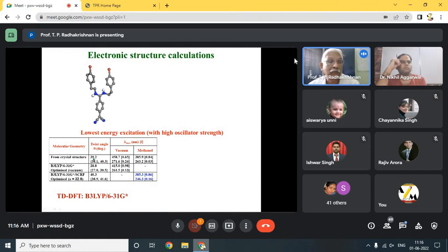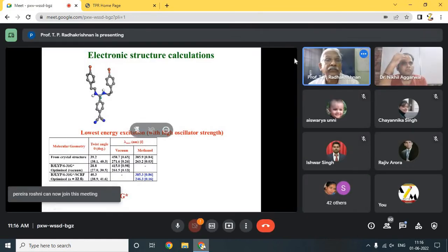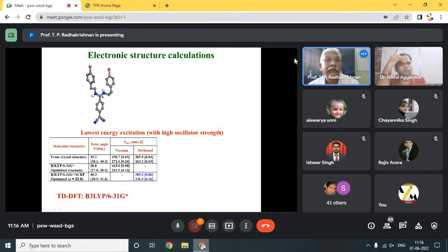as this picture shows. For example, just look at these numbers here. The twist angle, because these molecules are highly twisted. I forgot to mention this. That is this nitrogen atom here, the blue atom, this carbon, the following carbon, and the carbon here, they are not in a plane. There's a torsion angle between them, which is what we call the twist angle theta. Very critical parameter for this molecule because of the steric hindrance between this ortho hydrogen here and these groups. These things twist enormously. The twist angle is almost 40 degrees in this molecule from crystal structure.